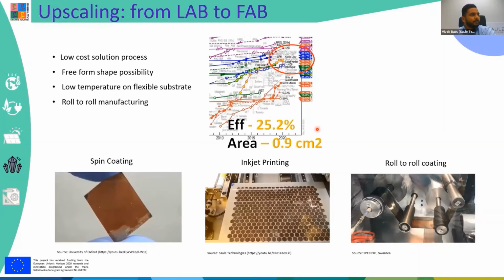Now I would like to mention also the efficiency of perovskite. If you see these small spin-coated cells, which are a small area, over the past 8 years it really shot up, and you can see it went to 25.2% efficiency, which is really amazing when you compare to other technologies where, for example, silicon took around 40 years to reach the highest efficiencies.